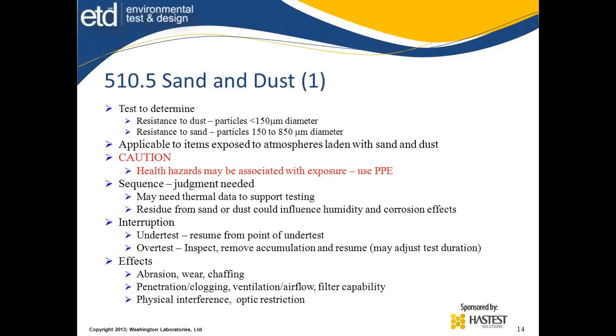Residue from the sand and dust can influence the humidity and corrosive effects. So usually this is done pretty well towards the end if you have to use a single test article. Again, this is one where a new test article, or something that hadn't had these climatic effects, could be the supporting piece. Vibration beforehand shouldn't be a problem. Temperature, probably not a problem. Humidity beforehand, possibly a problem. So you need to consider the sequence and deal with that in your planning.